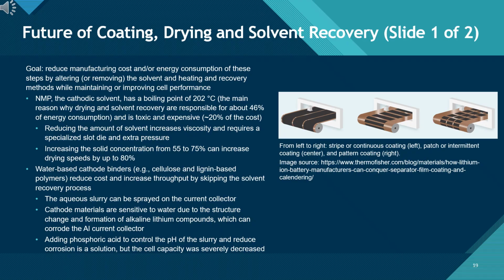Many cathode chemistries react with water, potentially corroding the aluminum current collector. pH adjustment strategies, such as adding phosphoric acid, help mitigate corrosion but currently cause significant capacity loss. The images illustrate three emerging coating approaches: continuous stripe coating, intermittent patch coating, and pattern coating, each designed to optimize material deposition and reduce drying demands.